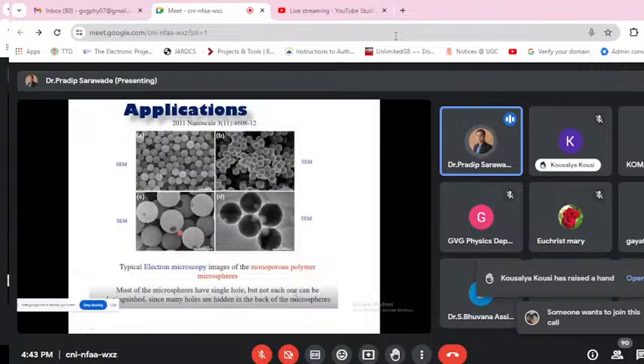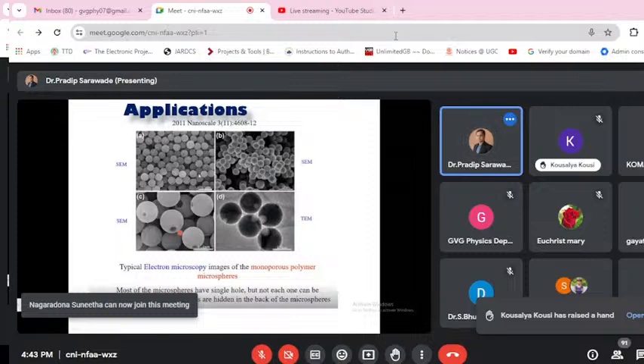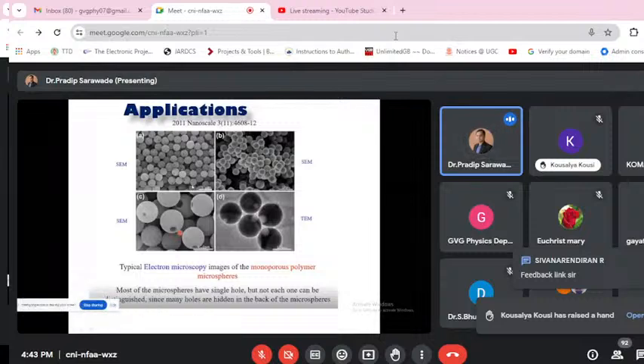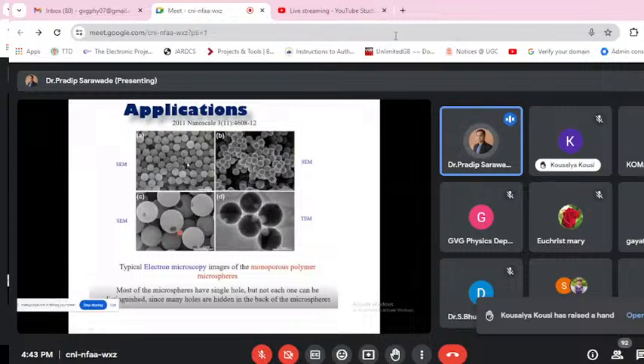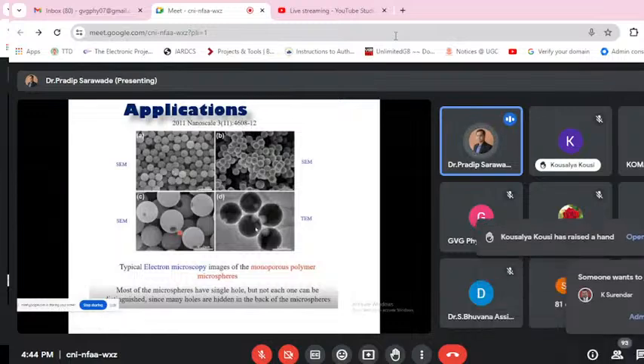As for applications of the TEM, even in SEM you cannot see, for example, a hollow sphere. Suppose this hollow sphere, just to show the advantage of TEM or HRTEM. Now see, this is the SEM image and this is the TEM image. Suppose I focus on this particle, you cannot confirm whether this particle is solid or hollow, because the backside you are not able to see. Now in the TEM, here you can see the contrast, right? From that you can say this sphere also has an opening at the backside. So from the TEM you can confirm it is a hollow sphere, but in SEM you cannot confirm that.